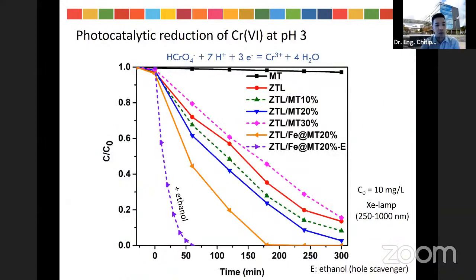And we apply this material for the chromium reduction at a pH around 3 because we want to avoid the co-precipitation of the chromium on the surface of the photocatalyst. And it's clear that the composite of the titanium layer double hydroxide with the Montmorillonite enhances the reduction activity of hexavalent chromium, which is a toxic form of chromium. And when we add more iron into the sample, in the orange color line, the photocatalytic activity is much improved due to the more generation of the new electronic state by iron atoms in the structure of the Montmorillonite and the lower energy band gap of the composite.